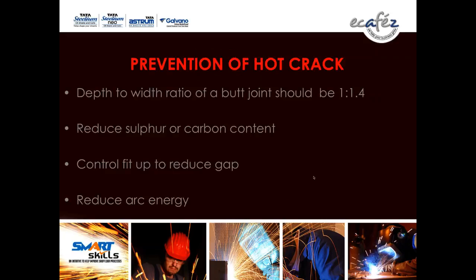Prevention of hot crack: depth to width ratio of a butt joint should be 1:1.4. Reduce sulfur or carbon content. Control fit-up to reduce the gap. Reduce arc energy. If you do that, hot crack will be prevented.